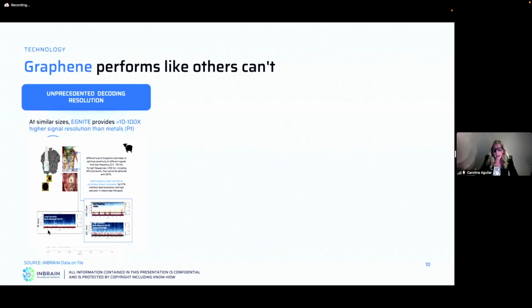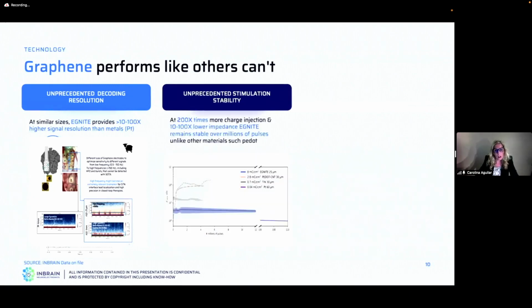And that's just by adding graphene as a new tool to understand what's going on in the brain. We have also seen that graphene has an unprecedented stimulation stability. As we said, we can inject 200 times more charge, but at a very low impedance. Indeed, when we compare platinum, iridium oxide, graphene, and other polymers like PEDOT, we saw that graphene has a similar stability over stimulation like platinum, but PEDOT, for instance, was degrading and changing in terms of impedance.